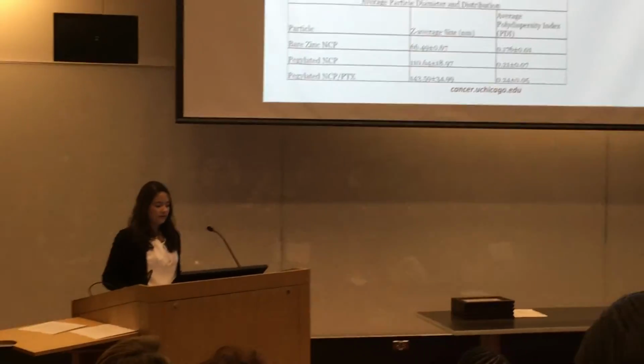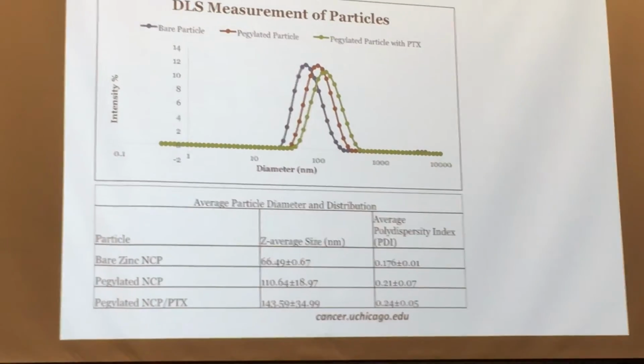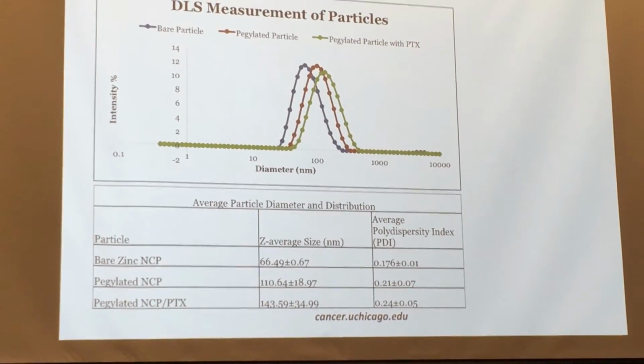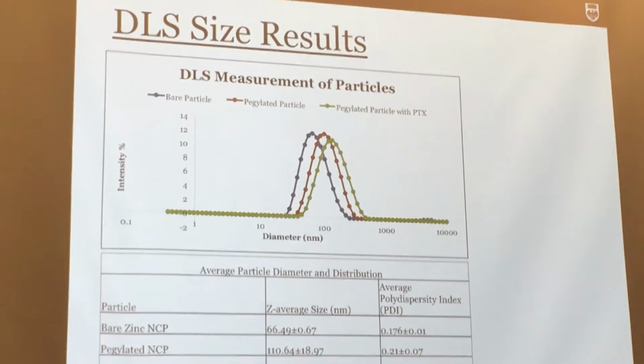Here's a graph showing the light intensity percent by the diameter of each group of particles: bare particles, pegylated particles, and pegylated particles with paclitaxel. As you can see by the graph and by the z-average sizes listed in the table below, bare zinc particles were the smallest, followed by the pegylated particles, and the pegylated particles with paclitaxel were the largest of the three groups. We also measured the average polydispersity index, or PDI, of the three groups.